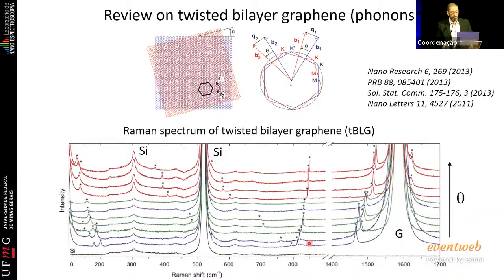this is the Raman spectrum. This is Raman shift, or Raman frequency, as a function of intensity. And every spectrum that you see here is for one given material with one different rotation angle or twist theta. This peak here, I will talk a little bit more, is the usual peak of graphene, but then you see the appearance of many peaks that are pointed by stars here, okay? These large ones here come from the silicon substrate.